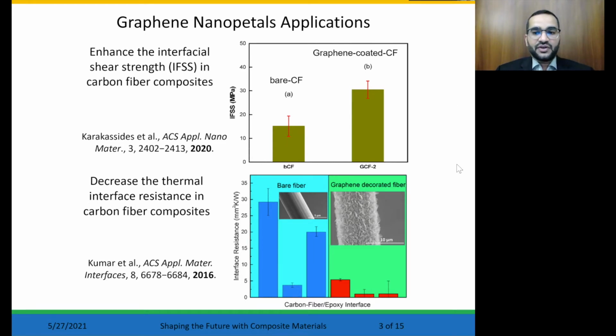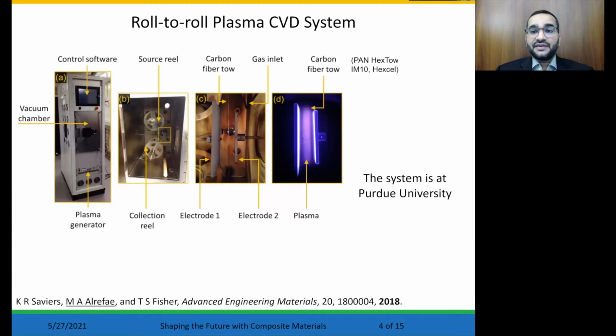Although vertical graphene or graphene nanopetals have been demonstrated for several applications, the mass production of these carbon nanostructures hinders their adoption in the existing industry. Therefore, a roll-to-roll plasma chemical vapor deposition system was custom designed for large-scale vertical graphene deposition. The carbon fiber tow is placed in the top roll, passes through the plasma region, and is finally collected in the bottom driving roll. Voltage is applied to the 2 parallel electrodes to ionize the gas and form a capacitively coupled discharge at a frequency of 80 kilohertz as shown in this image.